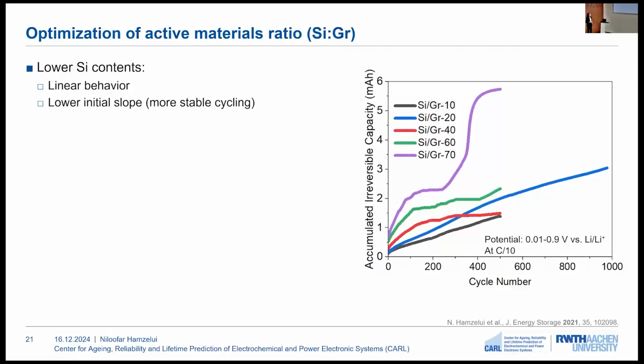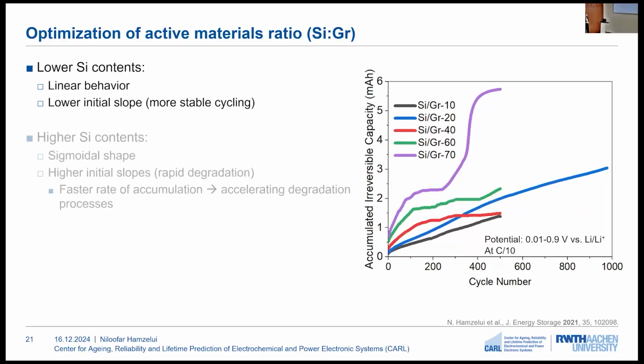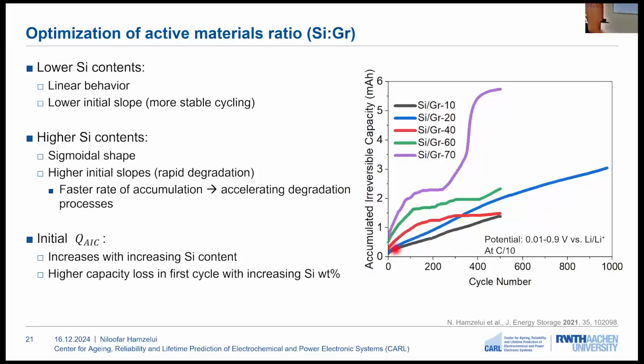As can be observed, at a lower silicon content, we have a more linear behavior and a lower initial slope, which indicates more stability of the cells upon cycling. By increasing the silicon content, we have a higher initial slope, which indicates a more rapid degradation, and the shape of the curve changes from linear to sigmoidal. This faster rate of accumulation can accelerate the degradation process. Also, the initial accumulated irreversible capacity increases with increasing silicon content, which shows that we have a higher capacity loss in the first cycle for the electrodes with a higher amount of silicon.